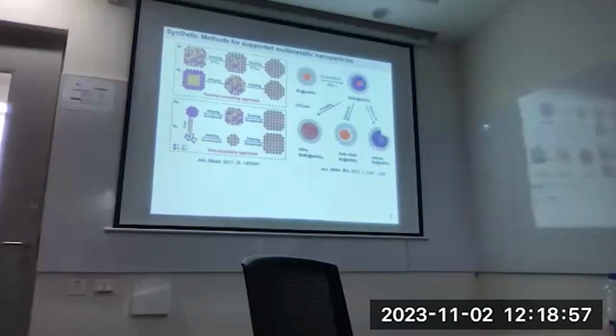Okay, so in my group, we would make these nanoparticles of platinum first, and then coat them with a shell of silica, which is porous. It is porous so that gas and liquid reactants can come through the pores and interact with the metal atom at the center. Then we would add another metal and form these alloys, all within the shell. The shell acts as a nanoreactor where you form these metal nanoparticles and then use them for catalysis. There is some issue of mass transfer, but then we use it to our advantage.